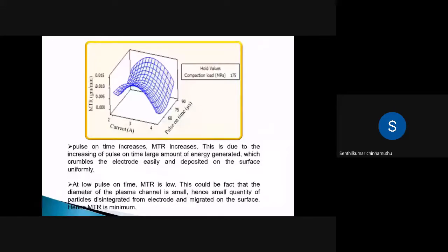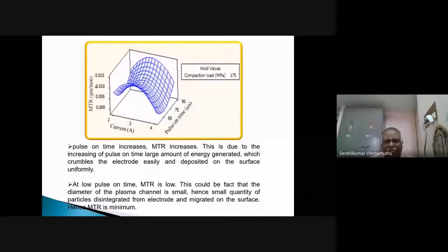and the surface property. See, the second figure shows the effect of metal transfer rate on current and pulse on time. The current value increases from lower to higher. See, from 2 to 3, the material deposition increases. Due to lower current, the material is dislodged, as I told in the previous graph. Similarly, 2 to 3, the material deposition increases, and then 3 to 4, it decreases. It declines because from 3 to 4, more energy is supplied in the interelectrode gap, and it melts and evaporates more amount of material. So conversely, the erosion takes place.